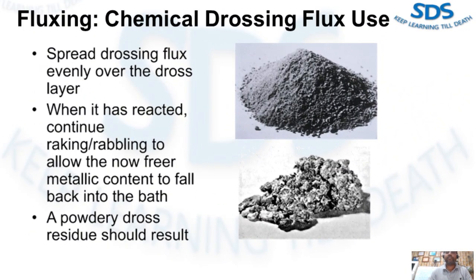Drossing fluxes are used to lower the metallic content of dross, which is the surface oxidation product that occurs at the bath surface during melting. Dross formation can be quite substantial, and further heat transfer into the bath through this phase can be diminished. Drossing fluxes contain fluoride that lowers the surface tension at the interface between aluminum and aluminum oxide. The drossing fluxes provide a localized exothermic reaction that raises temperature and increases fluidity.